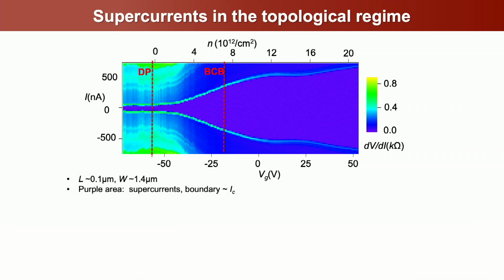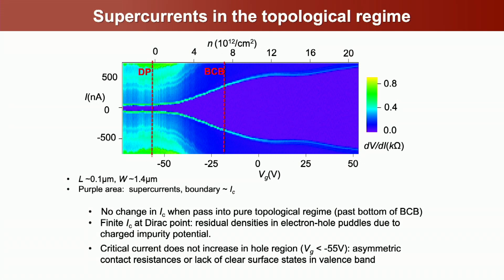And what we find by comparing this data, this is current, this is differential conductance, and so this bright blue line is the derivative of the conductance, which shows you where the critical current is. So this blue map tells you what the critical current looks like as a function of gate voltage as you go through the bottom of the conduction band and then the Dirac point. And actually, when we took this data, I was kind of hoping to see some big change happen as you went through the bottom of the conduction band. As you see from the data, almost nothing happens.